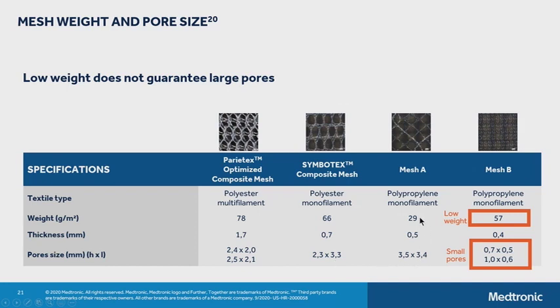When we look at mesh A, this correlation is true. You do have lower weight, and you can equal larger pores. So 3.5 by 3.4 with 29 grams per meter squared. However, mesh B is a polypropylene monofilament, a similar type of monofilament polypropylene. It actually has a low weight and small pores. So the correlation is not necessarily always there. So the ability to say, I can look at a mesh, look at the pore size and say, I know the density, is important. We believe that pore size is very important for how the material acts, how the host tissue responds to the mesh.